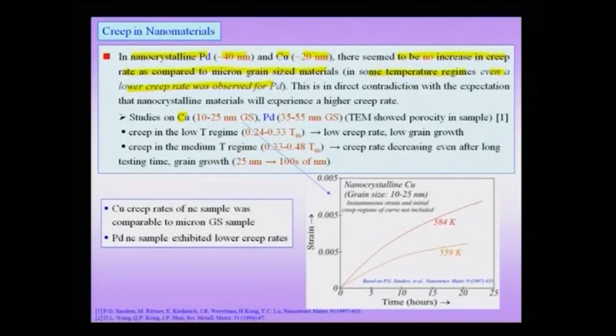Studies on copper, and here we are talking about a small distribution of grain size, which is 10 to 25 nanometer, and palladium about 35 to 55 nanometers, and here 40 nanometers can be thought of as an average in the regime between 35 and 55. That means, at the heart of the mechanisms, we have to keep in mind that though there might be an average grain size reported in literature, there is always a spread in grain sizes, and the more statistical data we get, the more we will find out the true distribution of grain size.